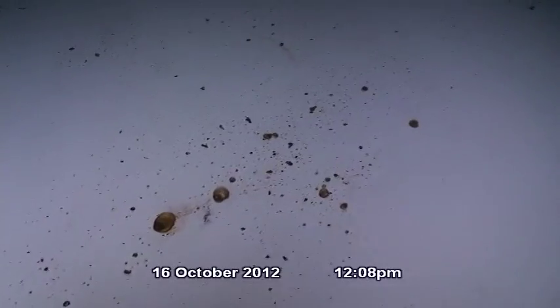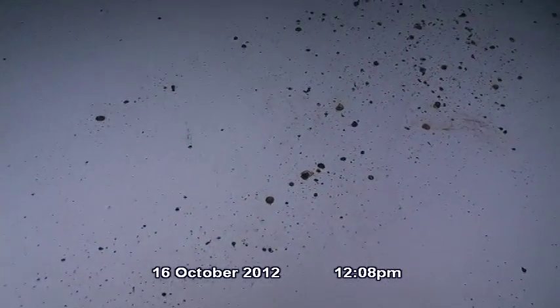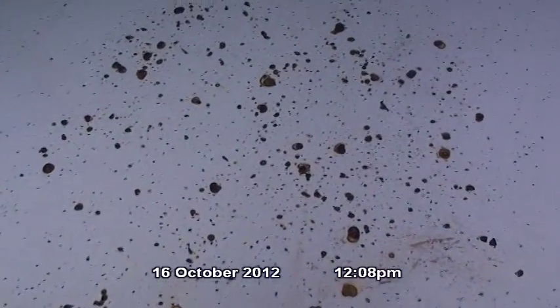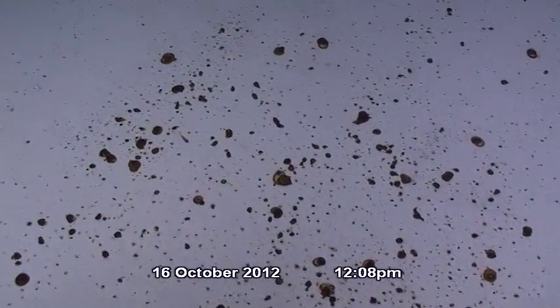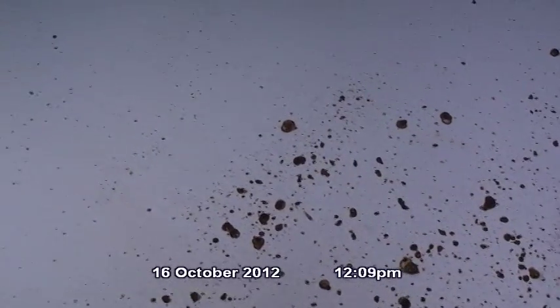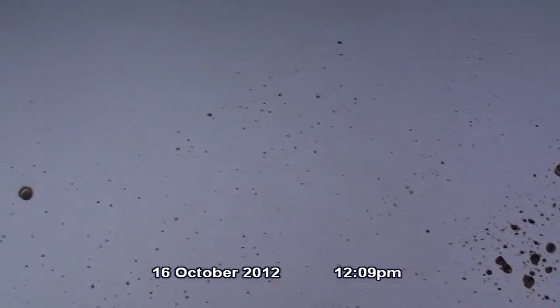Again, indications of vandalism or animal intrusion are not present on the interior of Upper Skycrest Reservoir. Here's a close-up of some additional areas of corrosion. The corrosion ranges from pinhole type to light surface corrosion in this area. Many small corrosion nodules are present. It does appear that the condition of the epoxy coating on the interior of the facility has significantly deteriorated since our last inspection.